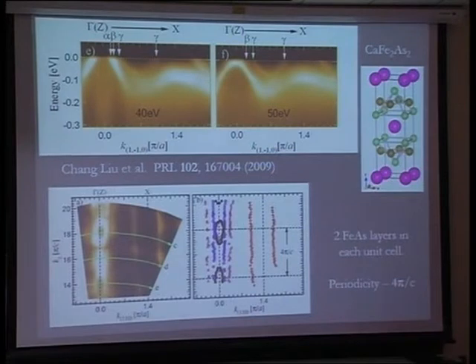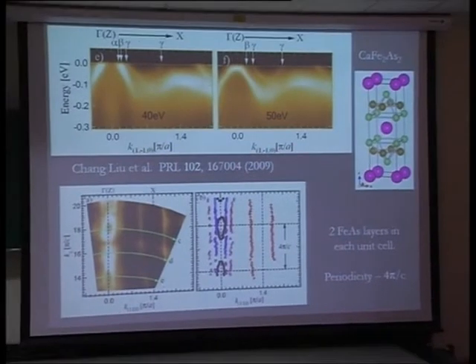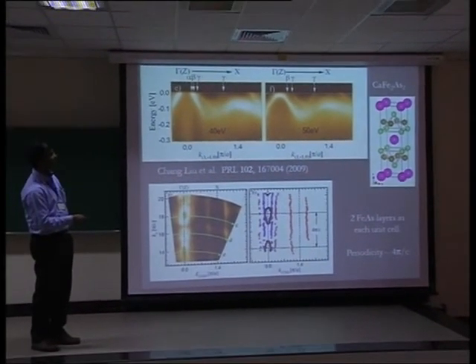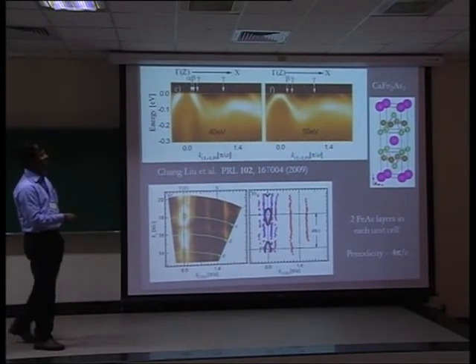So if you look at these different K, the numbers that you see at the left are essentially in units of pi by C. C is the C axis, so 2 pi by C should actually give you a gamma point translation. But here you can see that to get a similar point, you need to translate in the kz vector by 4 pi by C. So it means that your Brillouin zone somehow becomes doubled. This has been explained by the unit cell, which is like this. You have two iron arsenide layers within one unit cell. This is your C axis. Since these two symmetries are very different, but the electronic structure is somewhat similar or close by.